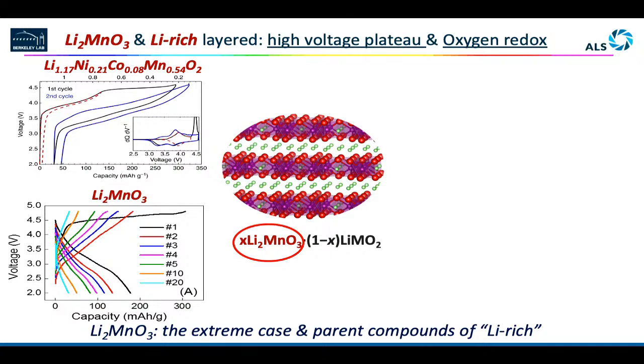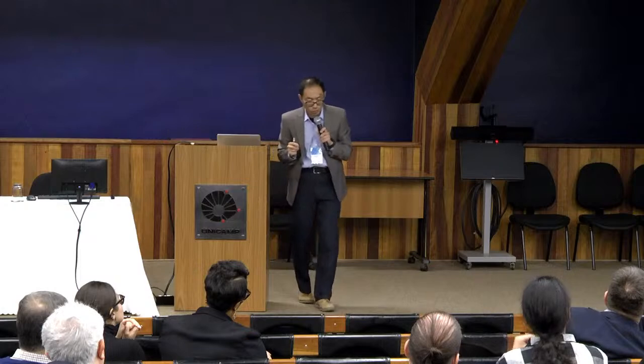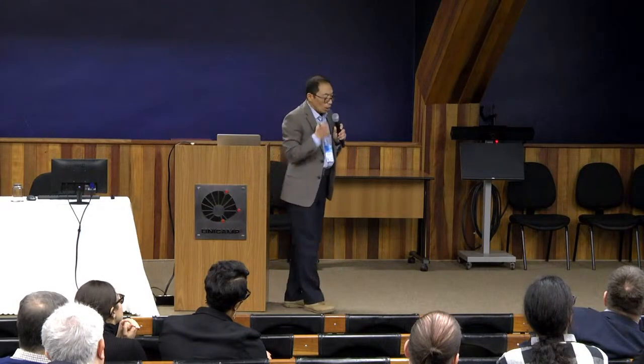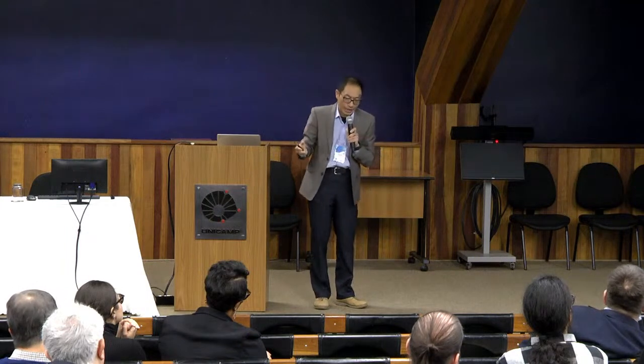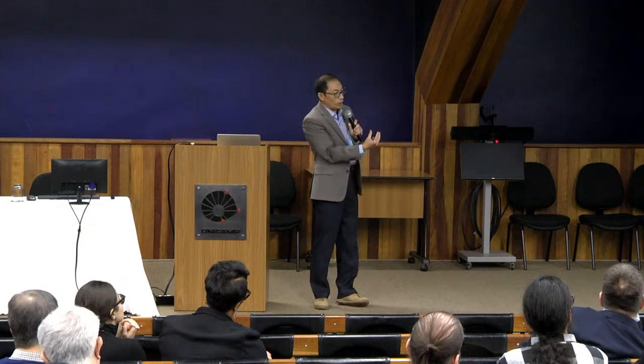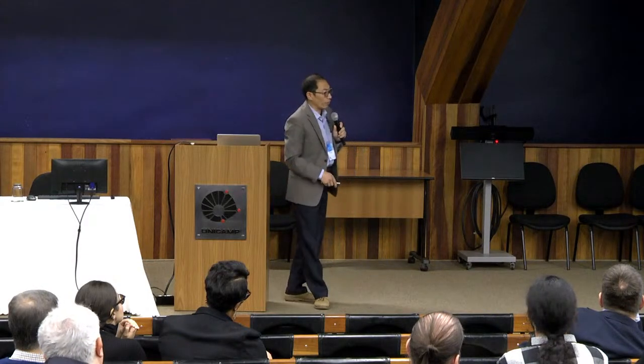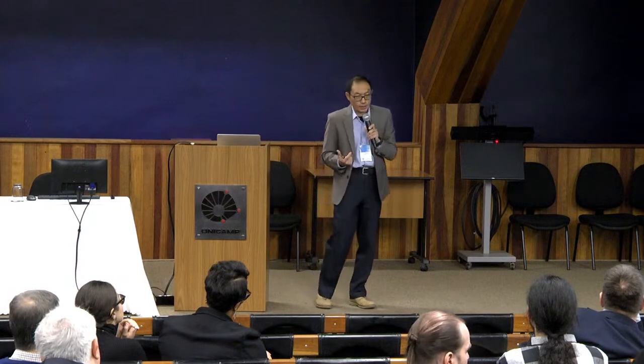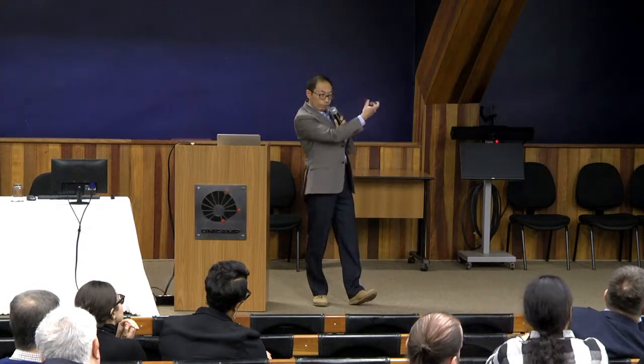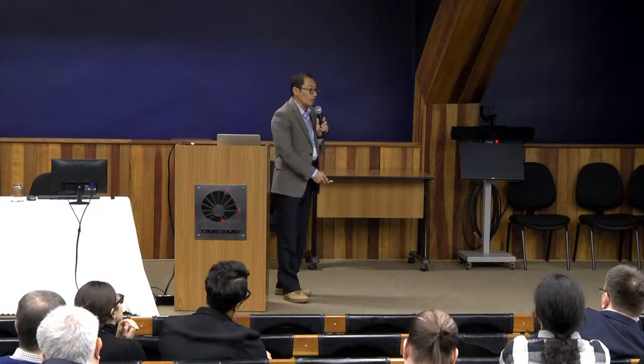So now you see the logic. It becomes natural to believe Li2MnO3 is the origin, is the material origin of the oxygen redox. And in fact, the papers with directly the title, Reversible Oxygen Redox in Li2MnO3. And this is the RIXS result. Once we have a tool to see whether there is oxidization and reduction in the material, and then we can tell whether there is really at least that kind of, meaning O-O bond forming type of oxidization and redox.